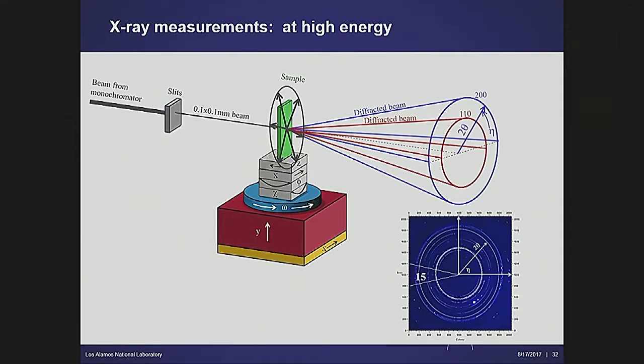At a high energy synchrotron X-ray light source, the typical mode is to take X-rays, if you're doing engineering where you have to get through appreciable thicknesses of some polycrystalline metal that is engineering relevant, you're typically operating at 50 to 100 keV.